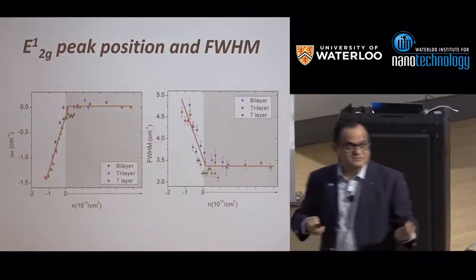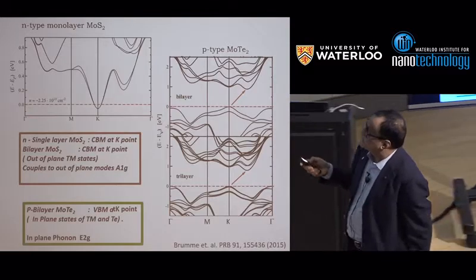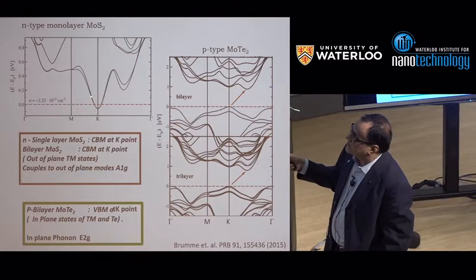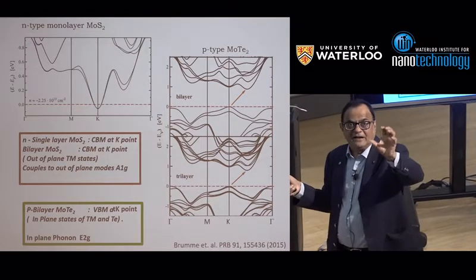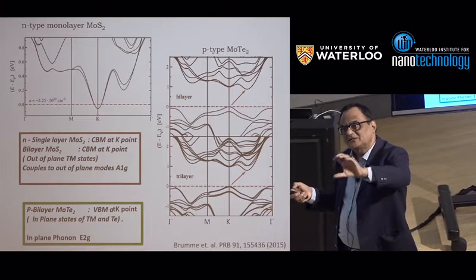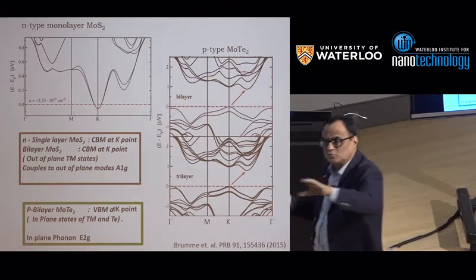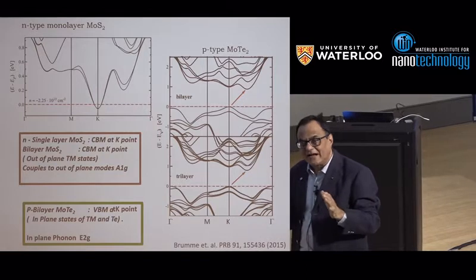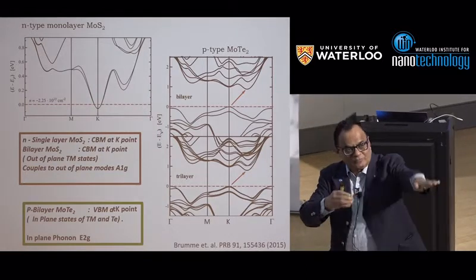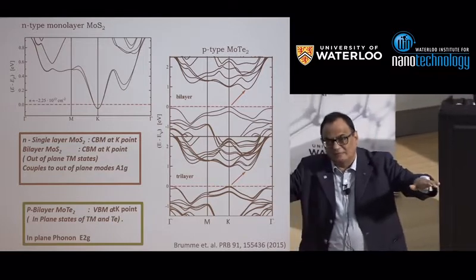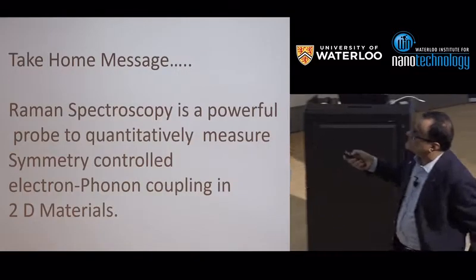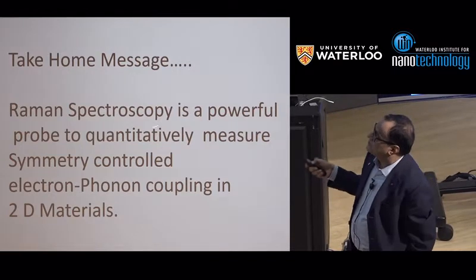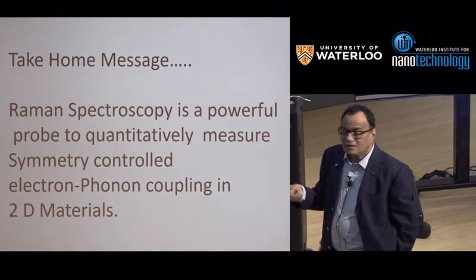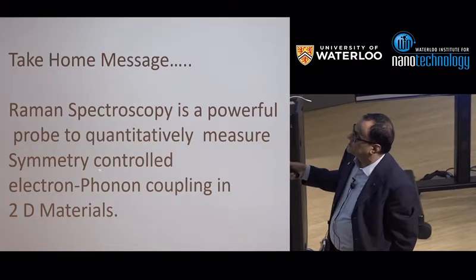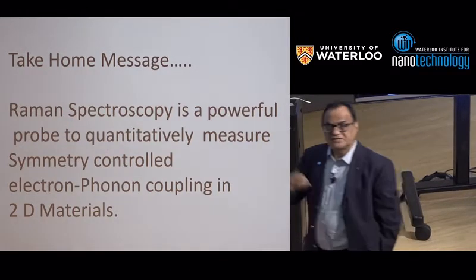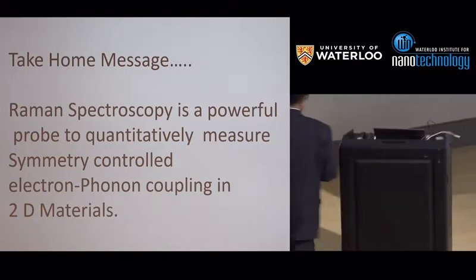And the reason, which is what we are deciphering, is related, again not going into detail, to the symmetry of the wave function at the conduction band. And the fact that the conduction band minimum is at different points in these two materials really is at the back of why the A1G phonon is affected in MoS2 and the E2G phonon is affected in MoTe2. So all this exercise tells us that Raman spectroscopy is not only for characterization, but it's a very powerful probe to measure symmetry controlled electron phonon coupling, which is again an important parameter to understand.